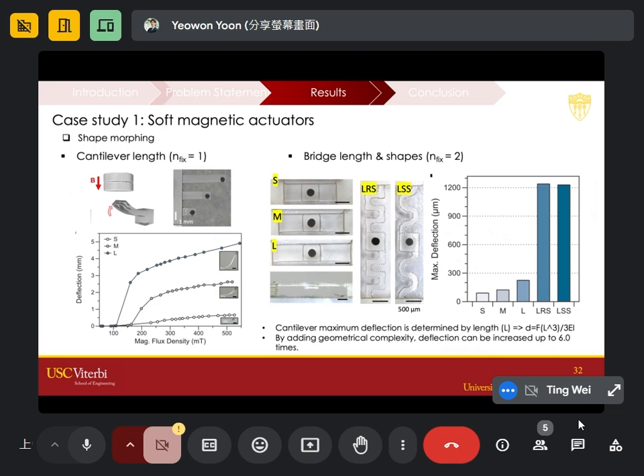And this is the one fixture of the suspended structure. If you fix it on two points, it becomes a bridge structure. I think most of you learned it from solid mechanics. This gives a more restricted actuation motion than a one-side fixture point. S, M, L mean the different lengths of the bridge, and LRS and LSS mean the serpentine structure. Using a simple idea to print different lengths, but if you incorporate this with a very flexible pattern, you can achieve about 6 times better deflection.